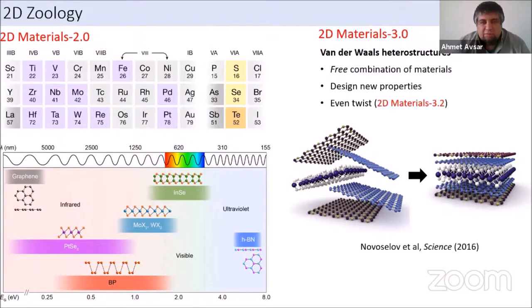It was shown that even the way you align these materials completely changes the electronic properties. For instance, if you take two semi-metal sheets and place them on top of each other, you can get superconductivity, or correlated insulators in these materials. That's one of the reasons this material system is very interesting. And since the discovery of graphene, there was always a question: can we also get a monolayer magnet, a material which has spin polarization at the ultimate thickness limit?